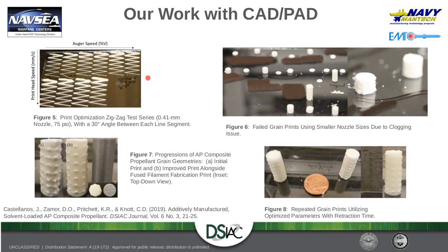So for our experiments, we decided to narrow down to 4 particular parameters. We decided to focus on the nozzle diameter, the print head translation speed, the speed at which the auger rotates, which directly influences how much mass is deposited over time, and the pressure of the pneumatic system being used to introduce the material from the syringe barrel into the auger system.